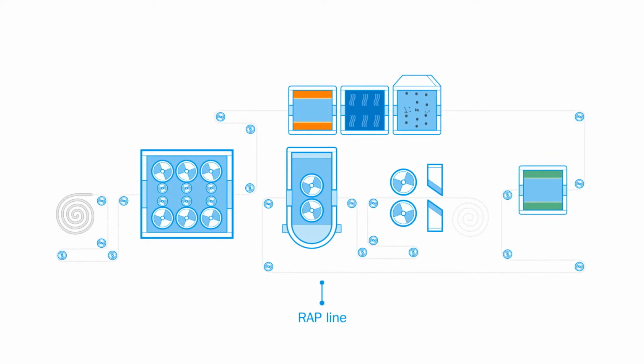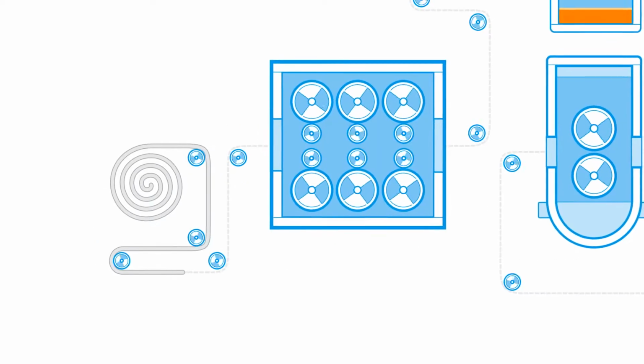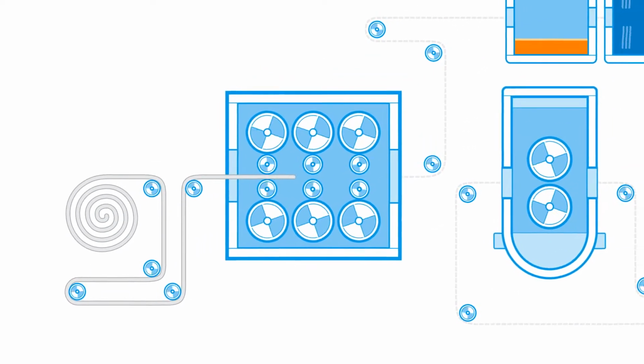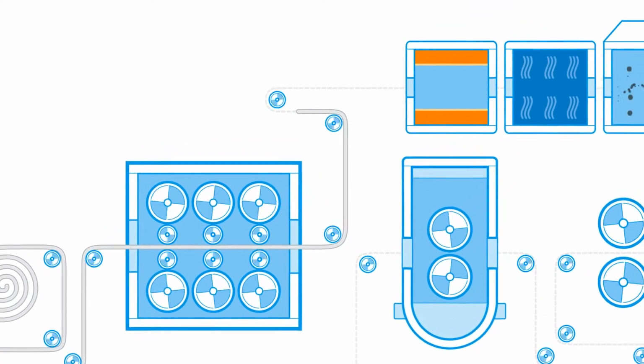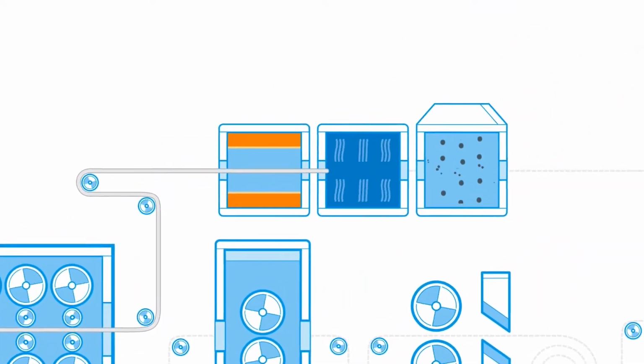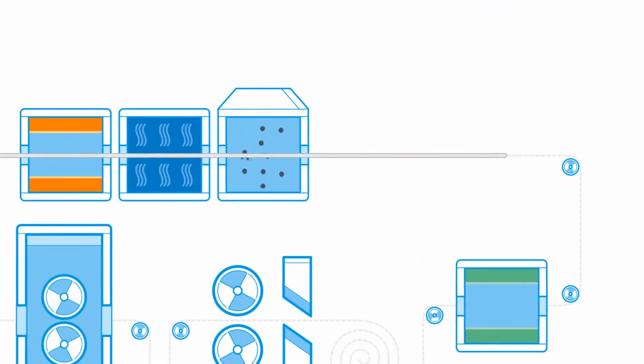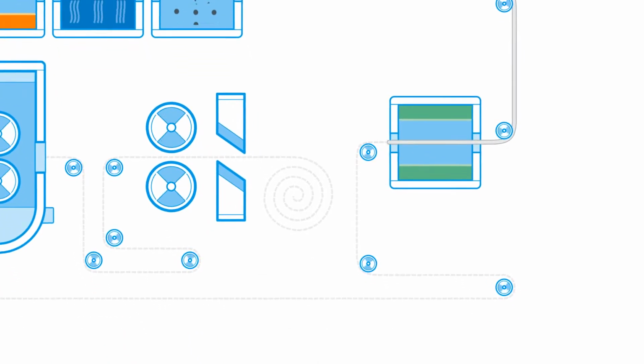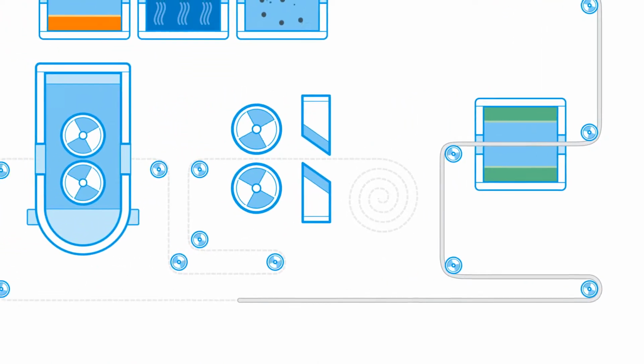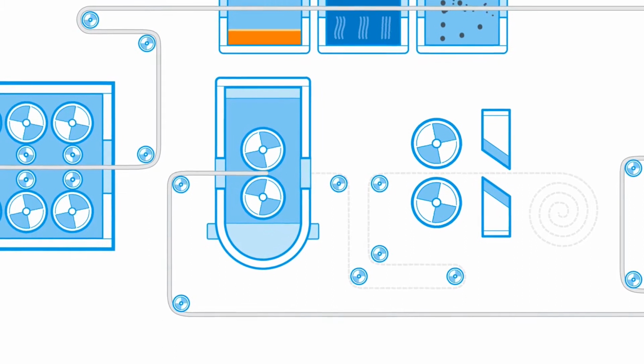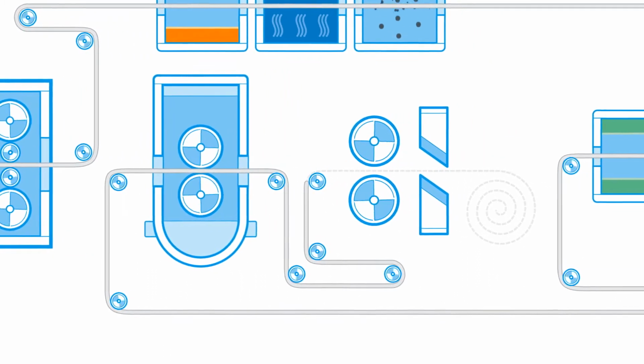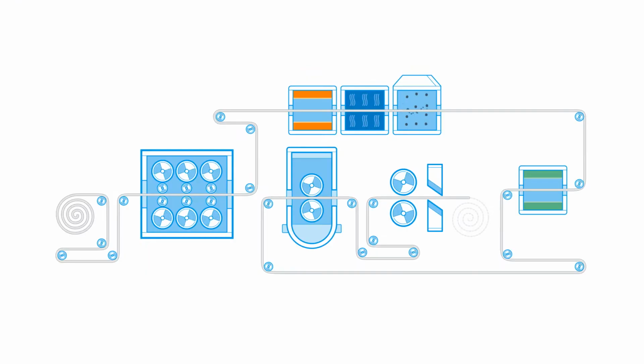A continuous rolling, annealing and pickling line, known as a RAP line, occupies all 3 floors of the plant. Steel strip passes through the RAP line twice. On the first pass, black hot rolled coil undergoes annealing and pickling and emerges as white hot band. During the second pass, the material is cold rolled and its thickness is further reduced. The final product is stainless steel cold rolled coil.